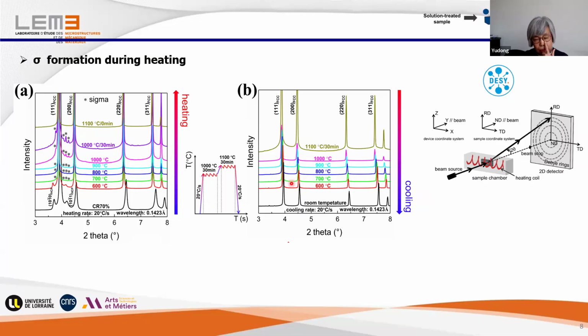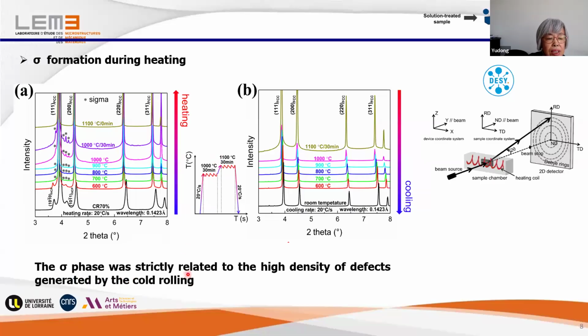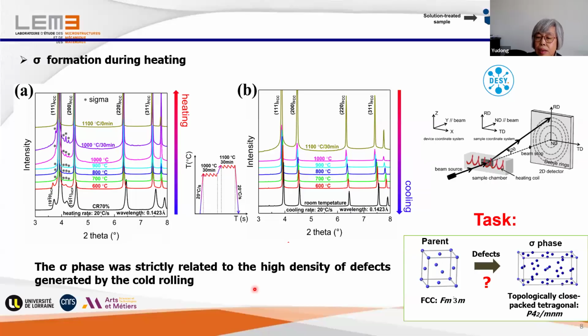According to the phase diagram, normally with the composition of this material, we should not have the formation of a sigma phase during heating from an equilibrium state. So this means the formation of the sigma phase was strictly related to the high density of defects generated by cold rolling. We know the transformation is from a parent FCC phase, and the sigma phase is a topologically close-packed tetragonal phase. So how did the transformation occur through atomic processes with the aid of crystal defects? With only synchrotron, we cannot see microstructure. We would like to know where these sigma phases form.